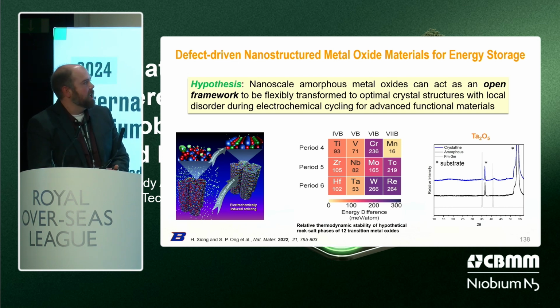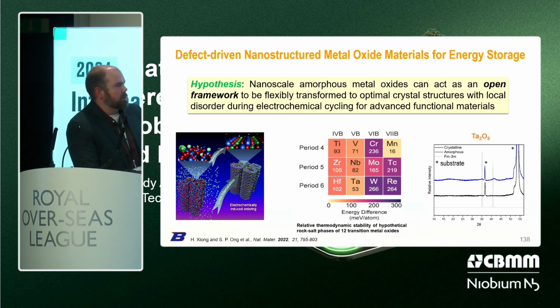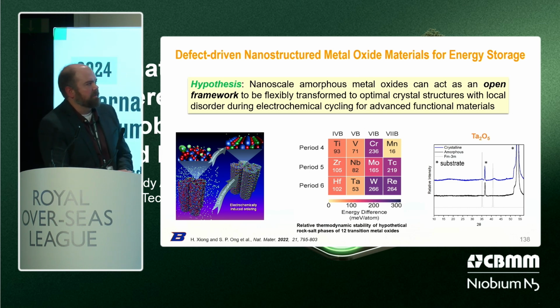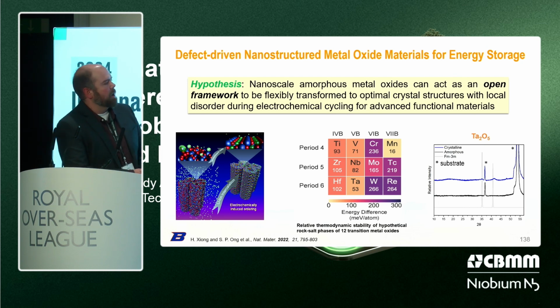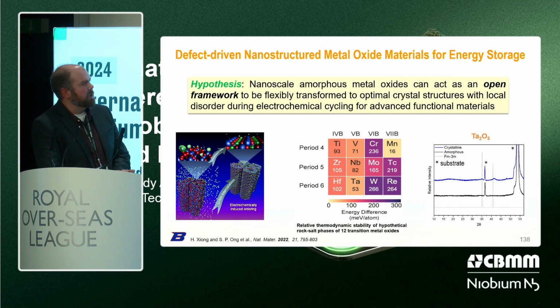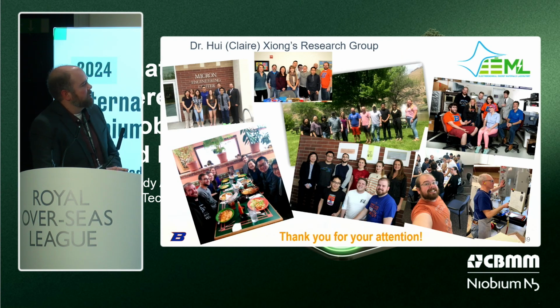And to kind of summarize that, we really want to look at these defect-driven nanostructured metal oxides for energy storage. And it can be such things as coatings, it can be full-on applications of these materials, but it really highlights this now. You can even look at there's another work on vanadium oxide that came out. So we have work in titanium, vanadium, and niobium. And this is unpublished results, but we have also seen this same phase transformation takes place in tantalum, but the capacity of it is a little bit low, and we're trying to figure out why that is at this point in time.